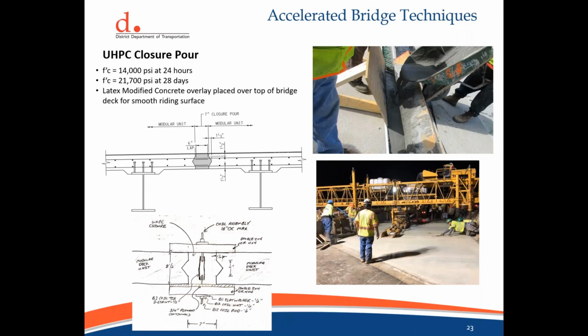We proposed an ultra high performance concrete pour to tie all the units together. This is also known as UHPC. This type of construction is very common when using accelerated bridge construction. In our design, we specified a design strength of 14,000 PSI at 24 hours and a 28-day compressive strength of 21,700 PSI.